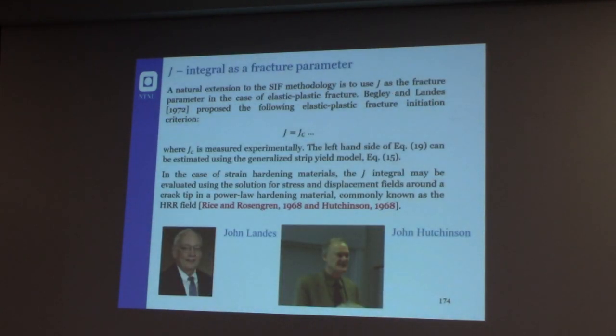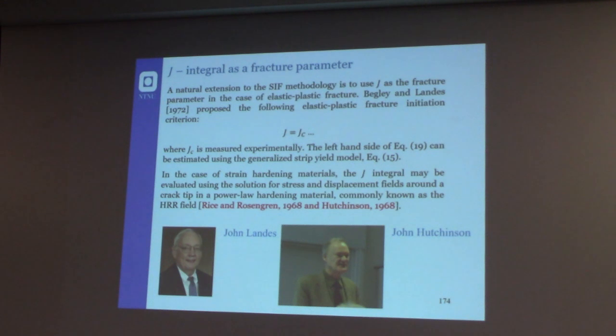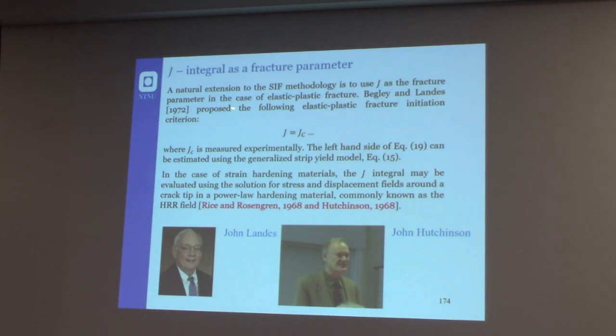But actually, locally, as I have shown before, plasticity occurs, and so sometimes the plastic field is not negligible, and we need to take it into account. And so there are also elastic-plastic fracture mechanics solutions. But of course, when you introduce plasticity, you lose the possibility of the superposition principle. So any time that you apply a load to your component and you obtain a solution, that solution is only valid for the applied load that you have applied to the elastic-plastic solution.